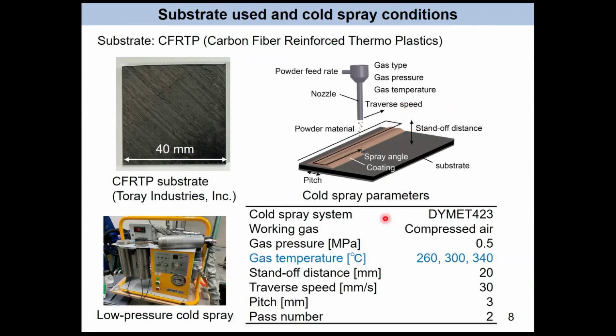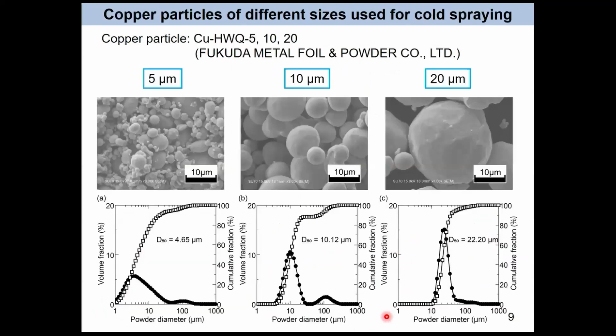We use a commercial low pressure cold spray system. The working gas is air and gas pressure is fixed at 0.5 megapascal. The standoff distance, traverse speed and other conditions are like this. And because we want to estimate the particle momentum effect on erosion of CFRP, we use 3 different size copper particles, with average sizes of 5 micron, 10 micron and 20 micrometers. So the particle size is doubled and doubled again. The particle shape is almost spherical.